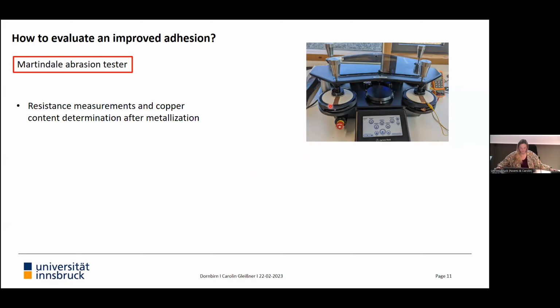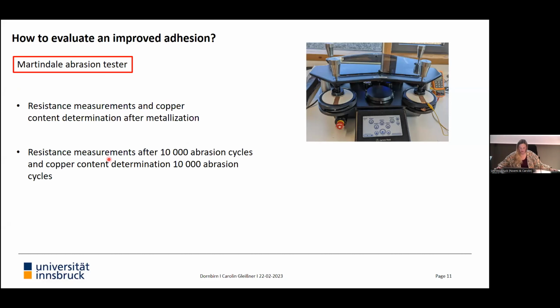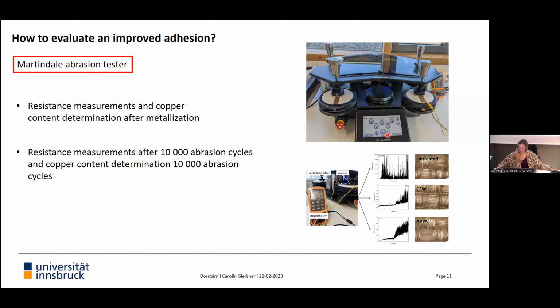And what I did was measuring the resistance and the copper content directly after the metallization. And then I also measured the resistance and the copper content after 10,000 abrasion cycles, which means there's a certain pressure, and this part goes forward and backwards. And so this is one abrasion cycle. You can also see here that I measured the resistance during these abrasion tests.